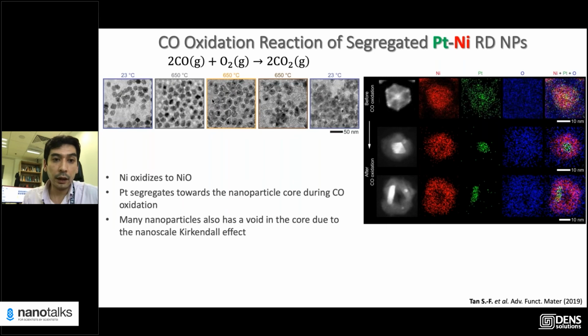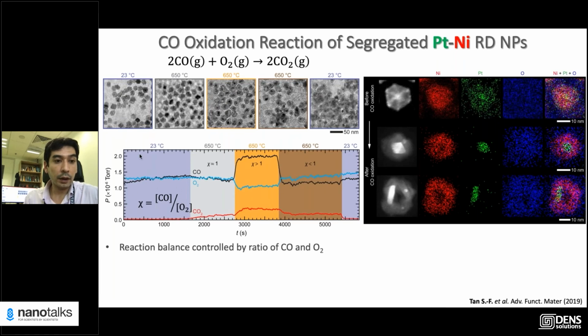This is again in situ imaging at different temperatures. You can increase the temperature, or you can change the gas composition. This chi just means increasing the ratio of CO to oxygen, and you can monitor the catalytic activity. But again, here you see all these subtle structural changes.